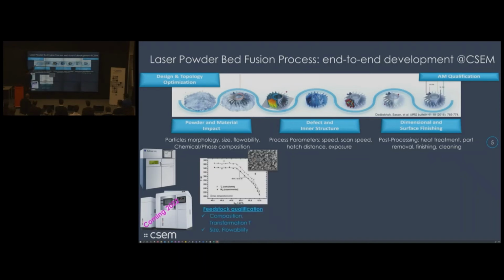So when this process is applied to laser powder bed fusion of nitinol, what does it mean? As I already mentioned, for feedstock qualification, we need a feedstock that has the right chemical composition, transformation temperature, and powder with the right size and flowability. For process development, we need to be assured that laser powder bed fusion gives us the right density and mechanical properties. Again, the composition can change during the process. We melt the material at high temperature, so we need to control the atmosphere. We have to be sure that what we get out of it again has the right transformation temperature and mechanical properties.